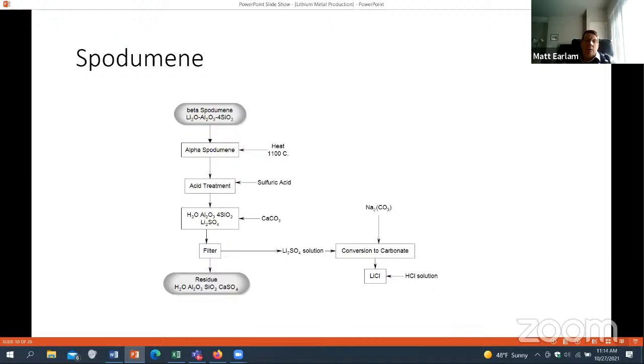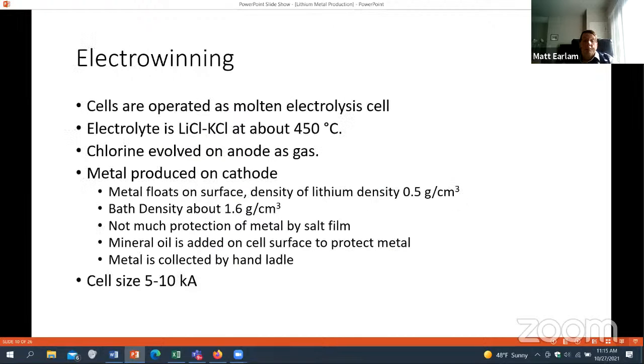So that changes the powder significantly to the point at which we can treat it with sulfuric acid and carbonate and separate the lithium sulfate solution from the rest of the minerals, which is basically calcium sulfate, silica, and alumina. And then once we get the lithium sulfate solution, we can convert that with sodium carbonate back to lithium chloride, similar to what we would do with a brine, except in the brine, we just produce the carbonate directly. We don't have this lithium sulfate intermediate step.